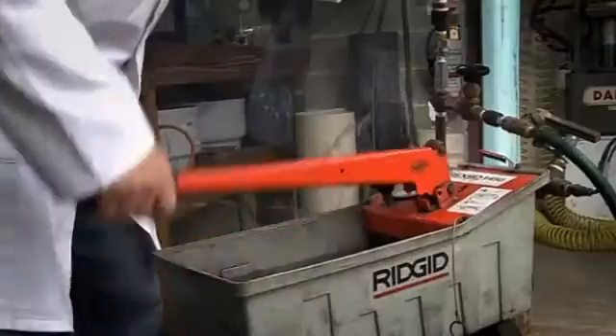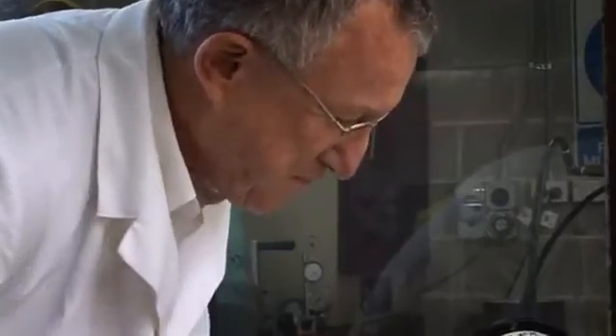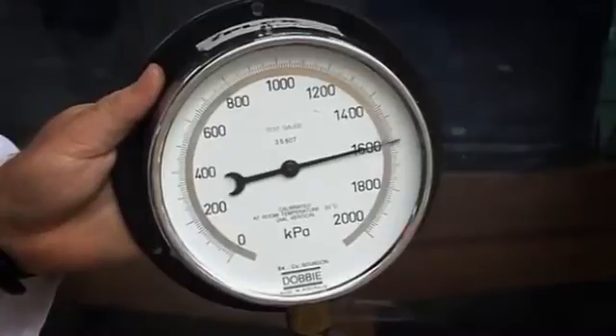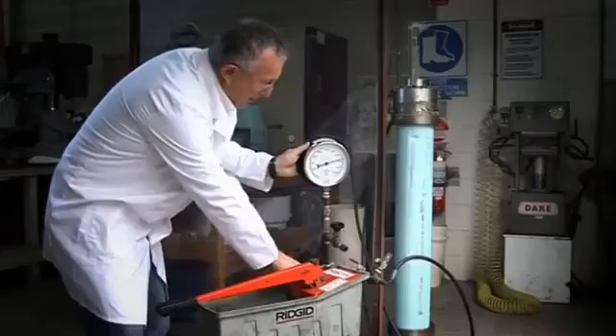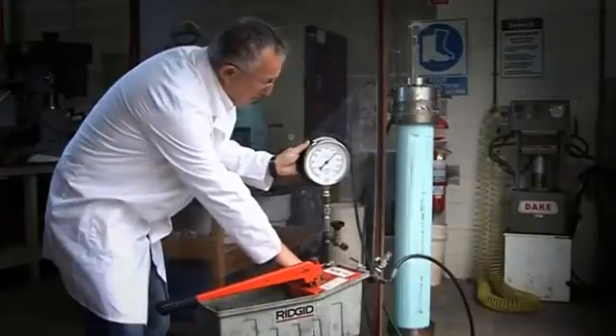The pipe was filled with water and pressure was applied whilst the PVCO pipe was monitored for leaks. As the handle was pumped, the pressure progressively increased, expanding the pipe and returning it closer to its original circular shape, until the pressure reached 1600 kilopascals — the working pressure rating for this PVCO pipe. The pipe did not burst and in fact no leakage was detected during the test.